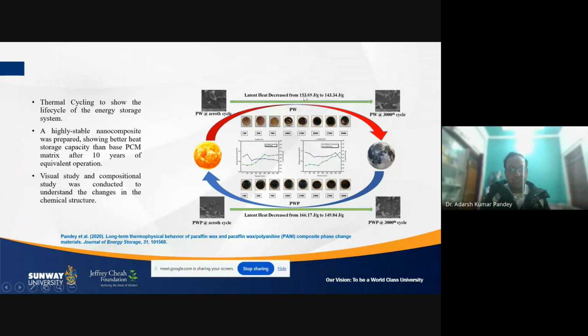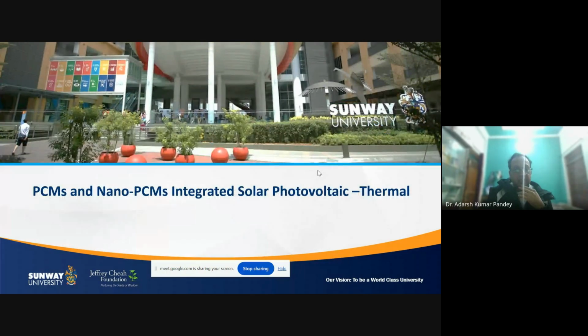But if you see, only paraffin wax at 0 cycle was 153, and after 3000 cycles, it was 143. But if you compare this with this, you will find out that even after 3000 cycles, the latent heat capacity is roughly comparable to the latent heat capacity of the paraffin wax at 0 cycle. So that is one of the very good results. That means if you are integrating this thermal battery into the system, and if you consider one cycle for one day, it can last until 10 years of equivalent operation. Okay, come to the solar collectors applications.